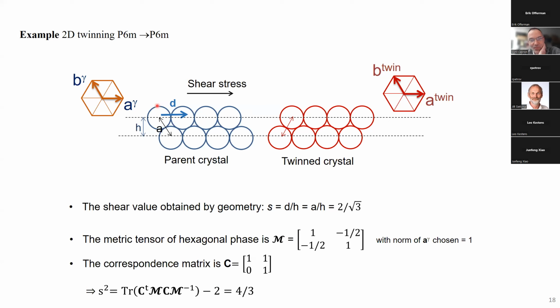For example, this is my parent crystal. I apply a shear stress and I shear it into a new orientation. Actually, it seems to be a new orientation, but it's exactly the same orientation. It remains hexagonal with the same orientation, but whatever. I have applied a shear stress and I have a shear distortion.